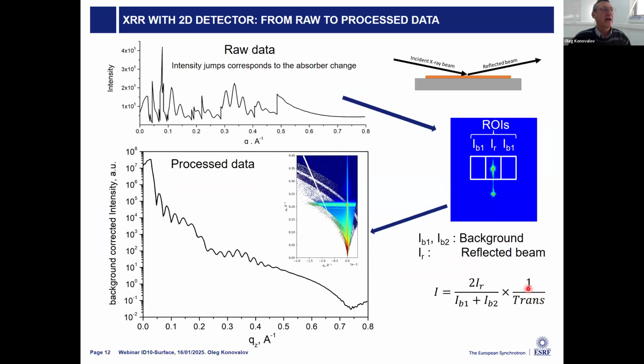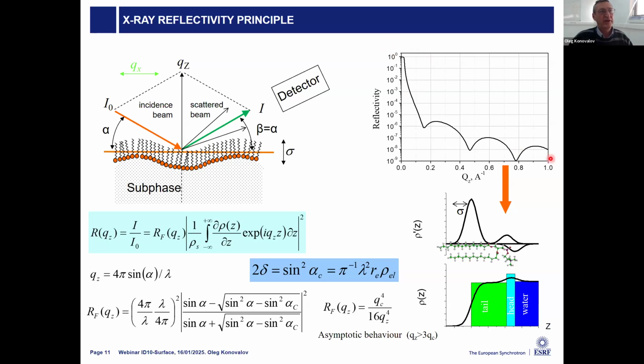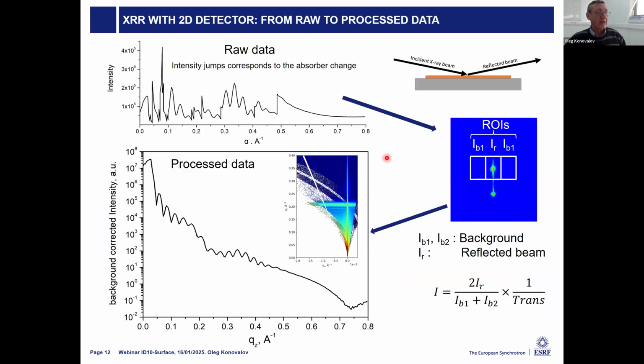So then how it nowadays goes at the beamline. As I told, we have an attenuator wheel which manipulates the intensity on the sample and detector. From the previous picture, you can see that intensity changes many decades on the sample, up to 10 power. But when we measure, the detector cannot measure above a certain threshold, and then we change the intensity of the beam. This is what you see during the measurements. This is done automatically: the position of the attenuator corresponds to the position which is safe for the detector. It looks like this during the measurements.